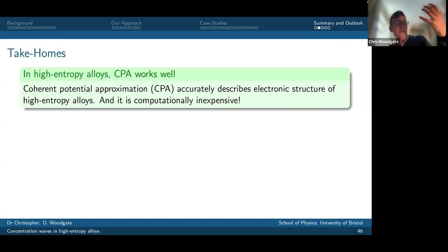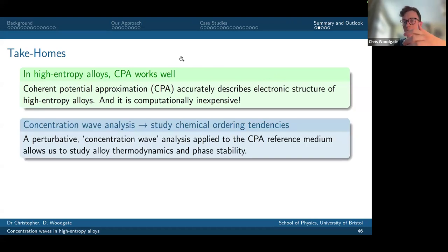Okay, so I've got 3 take-home messages for you. The first is that in high entropy alloys, this CPA does really nicely at describing the electronic structure of the disordered solid solution for very minimal computational cost. It's almost a renaissance of the CPA, these multi-component systems, because it enables you to do things very, very computationally cheaply while capturing a lot of the physics. The second take-home message is that this concentration wave analysis that I've outlined, and that I've had time to give you a couple of examples of, lets you study these chemical ordering tendencies. It's not quite as cheap as doing just a CPA calculation for the disordered solid solution, but you can still run it on a reasonably powerful desktop if you needed to.